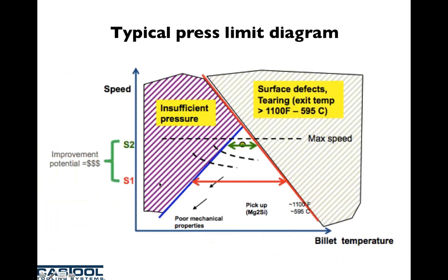What you end up doing is having to reduce your ram speed relative to your billet temperature. Every good extruder wants to control the billet temperature within, say, plus or minus 10 degrees or better, which enables them to operate as close to the peak in this area as possible. And again, our limitations here are flow stress on the left side, because in this area you don't have enough pressure on your press, and these are the actual alloy effects. As you get above these temperatures, you have tearing and other defects.